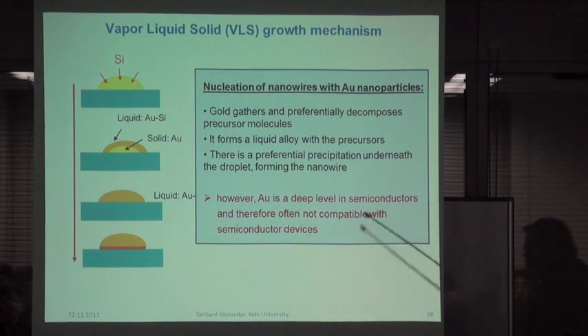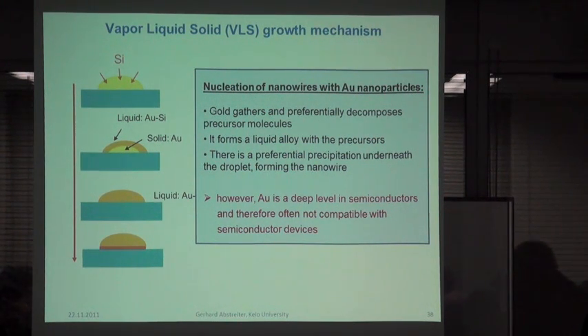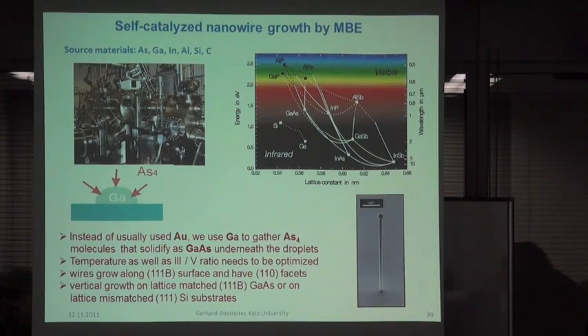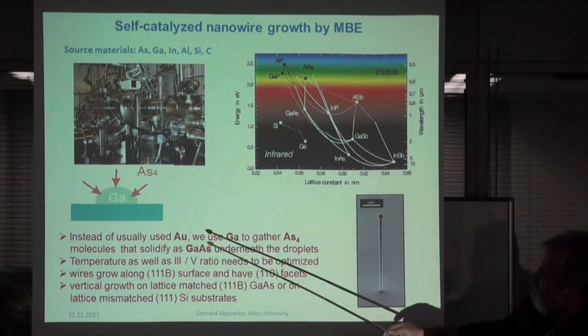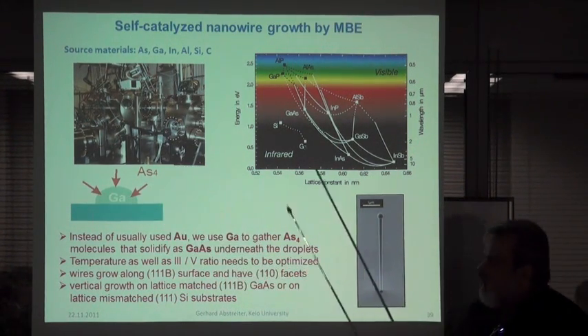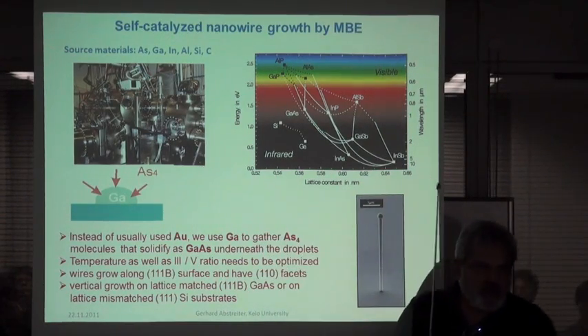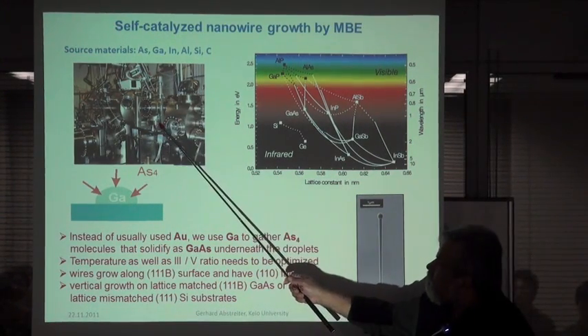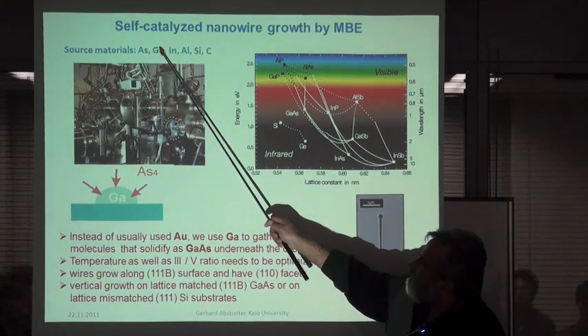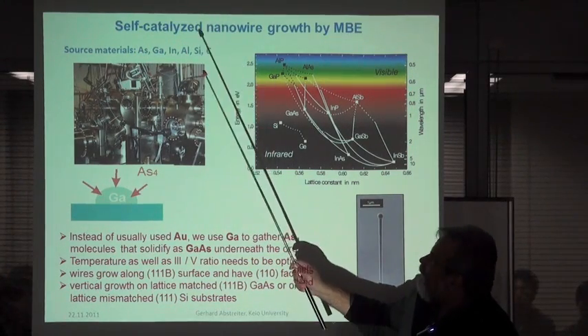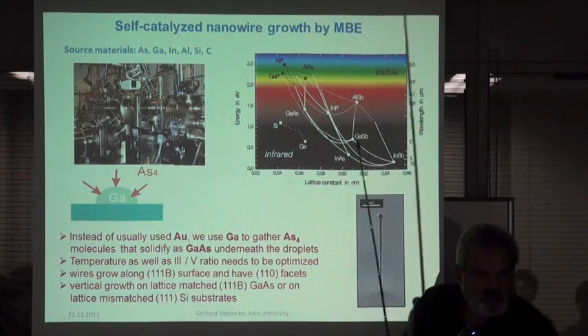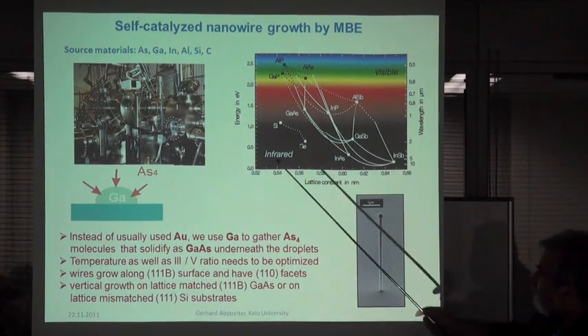Now gold is, however, a deep level in semiconductors, and therefore often not compatible with many things. That's especially silicon. People don't like gold at all. In III-V it's not so important. So what we tried a few years ago, if we can replace the gold by gallium. And so we used again our ultra high purity MBE machine. So this is a III-V MBE machine where we have as source arsenic, gallium, indium, aluminium. And as dopant we have silicon and carbon. So for N and P type dopant.